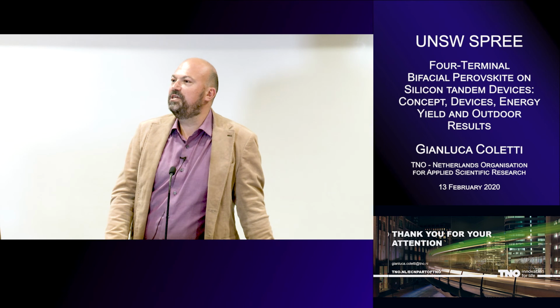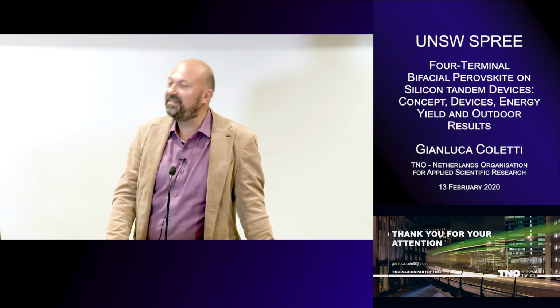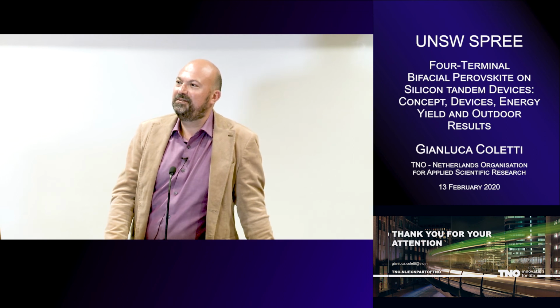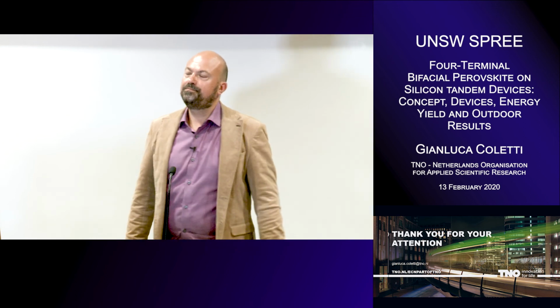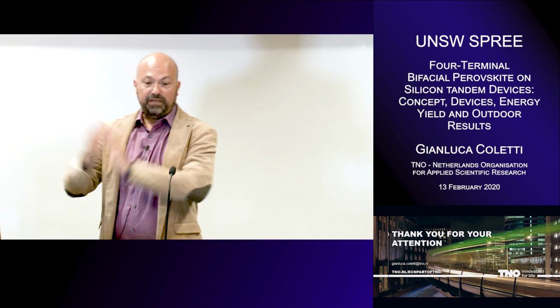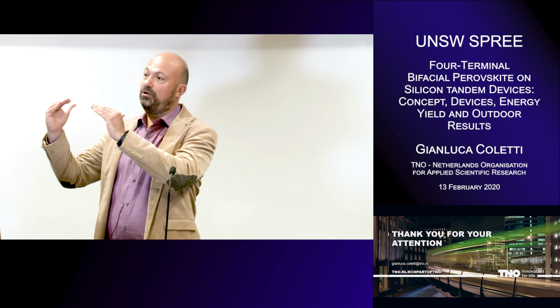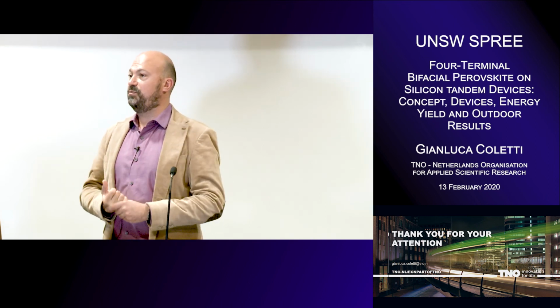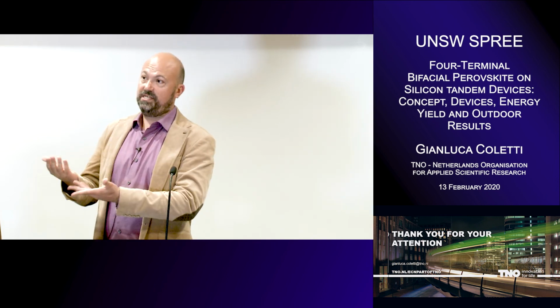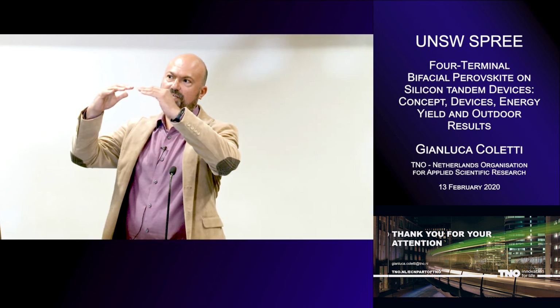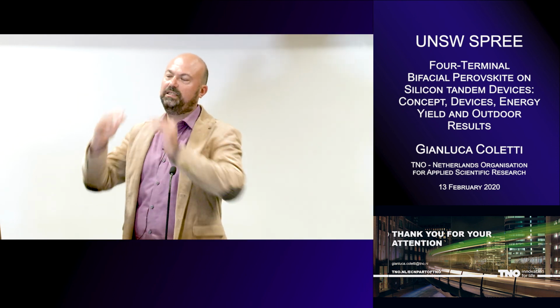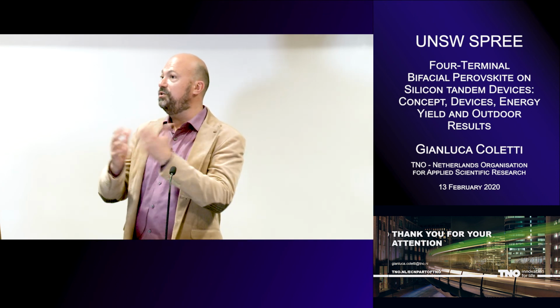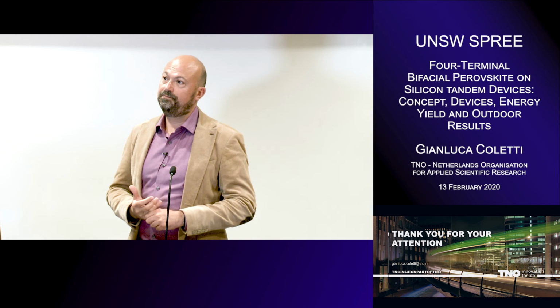It's something to consider when you want to be accurate, and it's something that we are implementing, but we don't have yet. So as you change the conditions, you wouldn't necessarily change how you'd measure it. You might get a lower total intensity if you have less reflection. If it's just a shift, not, and it depends on the spectral response of your device, the bottom device in this case, where for silicon it's pretty flat in all that range. Actually, it could also be beneficial because you have a cut on the UV, which is normally not used.